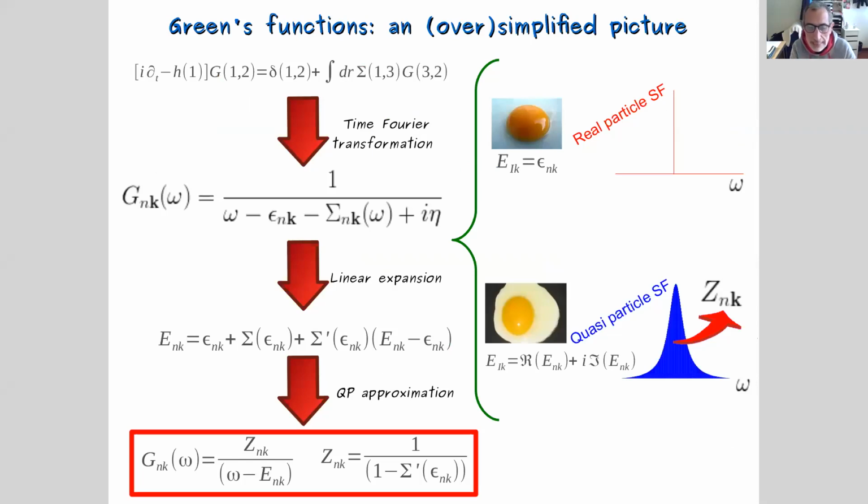So now, where do the electron-phonon effects actually come from? Always from the self-energy. At the end of the story, the electron-phonon effect is just one contribution to the self-energy. In GW, you have seen in the tutorials the screened exchange and everything. But if you include electron-phonon corrections to the self-energy, you get the new self-energy, and through the Dyson equation, you get the corrections to the levels.